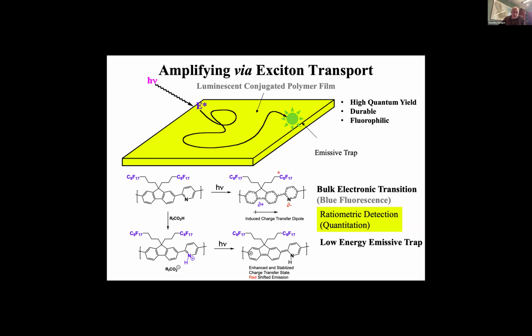Now, the way we create activation in these is we have these polymers that again have these pi systems, and you might notice there's this pyridine, this nitrogen here in the ring. The perfluoroalkyls tend to sequester the PFAS we're looking for into the bulk of the material, and that PFAS brings a proton preferentially rather than a sodium ion, because this is a very hydrophobic environment.